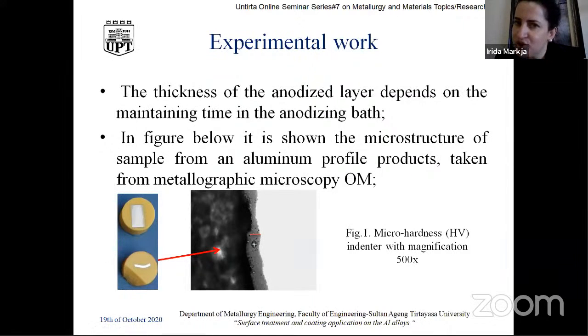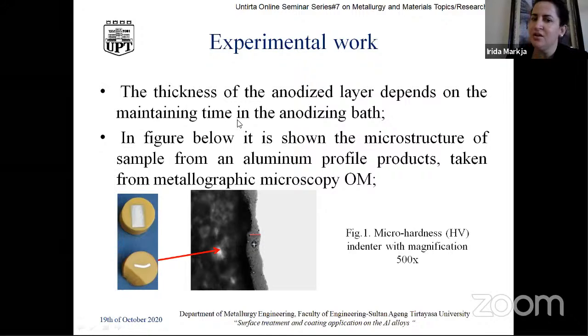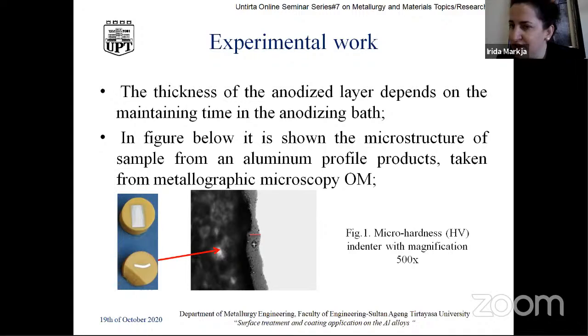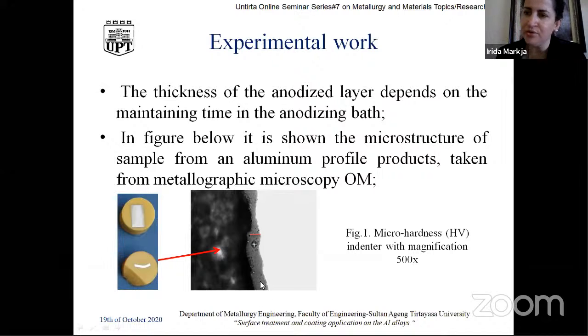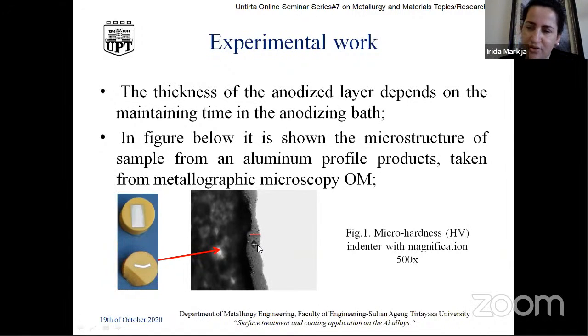Also, part of the research, of the experimental work, is focused on the thickness of the anodized layer, but in the meantime maintaining the time for the anodizing bath, which is important for the results and for the properties that the oxide layer will achieve after the experiment. These are samples that we have prepared, two planes or two sections of the samples. And this is the microstructure and the oxide layer that is created after the anodizing process. And here is one indentation, which we have taken from the optical metallographic microscope.